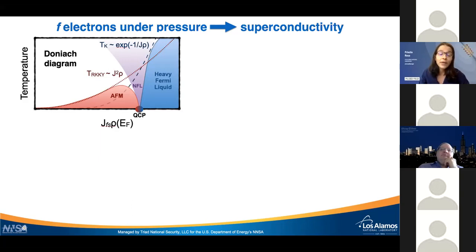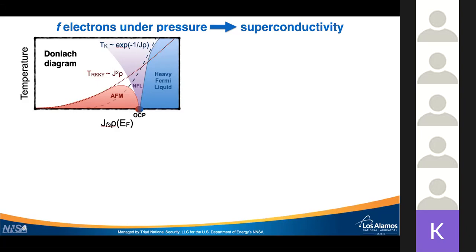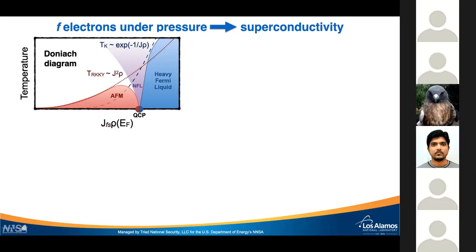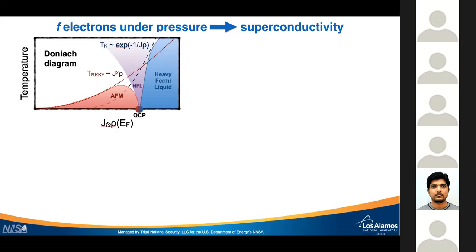And if we increase the coupling J, or the density of states, or the combination of both, then we'll go towards a maximum of T_N of the antiferromagnetic order, and this order will be suppressed towards a quantum critical point. So we have a second order phase transition being suppressed to zero temperature. At this point, we have something that is not Fermi liquid, and we have really strong fluctuations. I like to think of this as a buildup of entropy that has to be relieved in some way. And often it's the case that superconductivity is the way nature chooses to relieve this entropy and create a new ordered state around this quantum critical point.